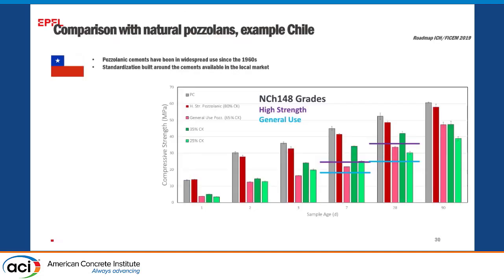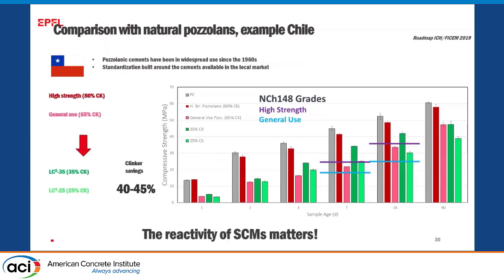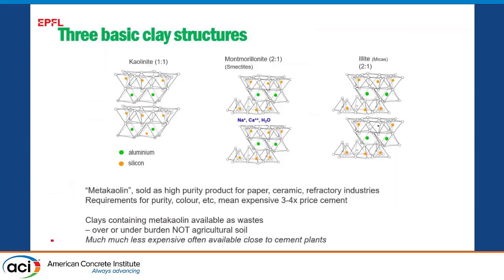You've got a lot higher reactivity than things like uncalcined pozzolans. This shows an example of work we did comparing the pozzolan used in Chile, where they have quite a reactive pozzolan, but we could get the same performance with lower clinker contents by 40-45%. So things like fly ash and natural pozzolans can do a really good job of controlling things like alkali silica reaction, but it's really difficult to go to these high replacement levels you need to save CO2.